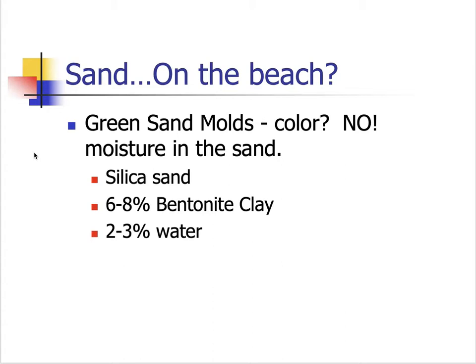Typically, sand molds are green sand, or it's the most popular anyway. And when we say green sand, what we mean is that it has moisture in it. It's not green in color, usually, but it's usually more of a black color. It represents kind of like when you have clay and it's not dried out or fired yet. It's called greenware or green. And it means it has a little bit of moisture in it. So we have silica sand, we have bentonite clay, and we have water.